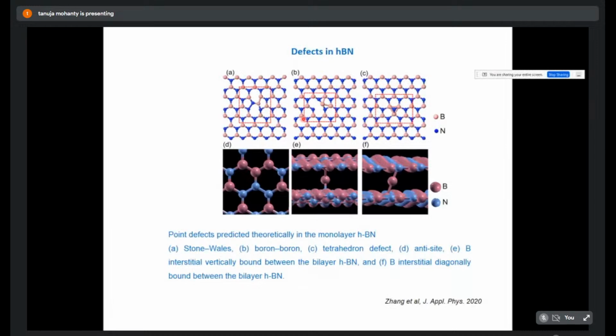Then there is a boron-boron defect. And then the tetrahedron defect, where a tetrahedron is created, and somewhere there is the anti-site defect. Anti-site means, in general terms, the ideal place for an atom: if it is a 2-atom molecule, then wherever B and N should ideally be placed, if they are not in the same place or they have interchanged places. Suppose here there are 6 bonds, but this place ideally should have gone to nitrogen, as you have seen here. Instead of going to nitrogen, there is a combination of only boron like this. So this variation is called the anti-site.